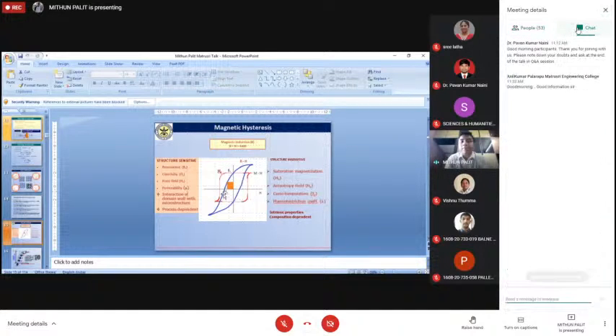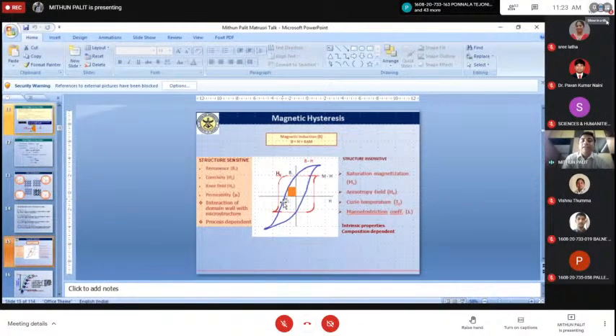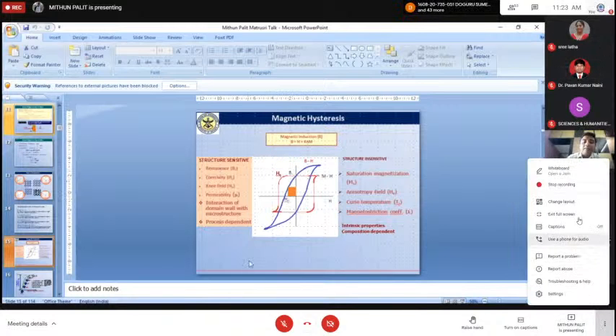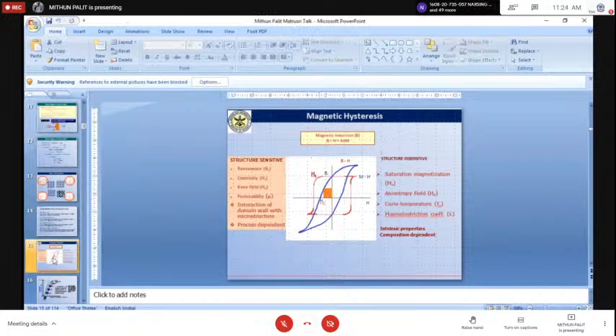As I explained before, B equals H plus M, and this loop we are seeing is basically the M versus H loop. You can as well plot the B versus H loop too. That is shown in the blue plot. And now you can see that from the blue plot we get one kind of coercivity, which is lesser in value. From the red plot, we get another type of coercivity. The coercivity we get from the red plot is called the intrinsic coercivity of the material, and the one we get from the blue plot is called the coercivity of the material.